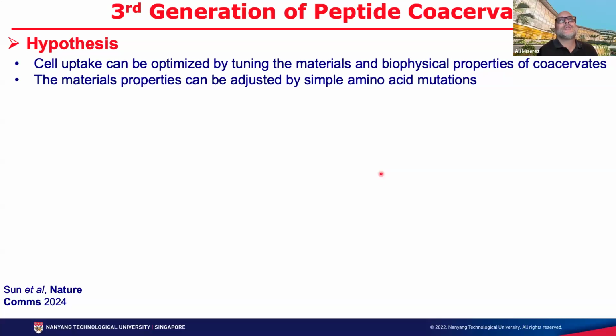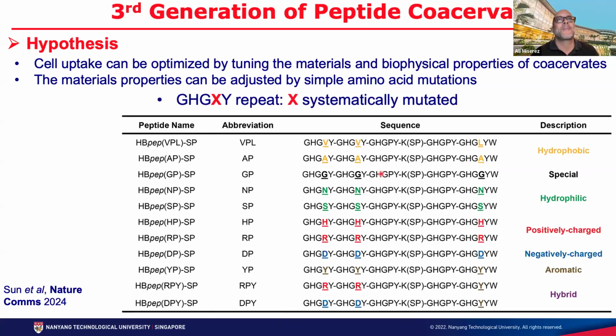And I just want to show you that now that we have those coacervates made of a fairly simple peptide, only 26 amino acids long, you can modify the sequence of the peptide and then improve the uptake further. So this is the sequence of a peptide, the amino acid sequence. You keep most of the amino acid residues the same, but you change some in very specific locations, you do some specific mutations. We make those peptides by solid-phase synthesis. For instance, you may have an aromatic residue in this fourth position, or a charge, etc. So we can just change two or three amino acids.